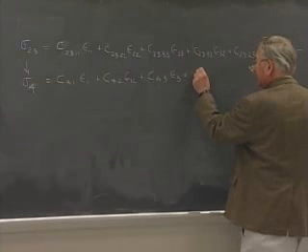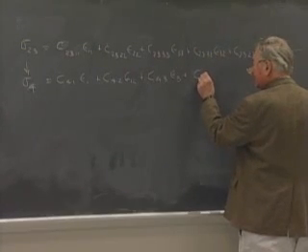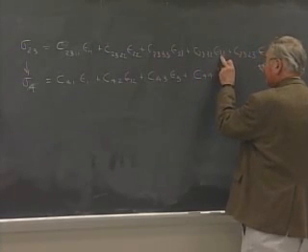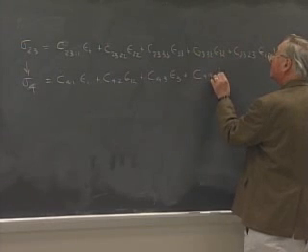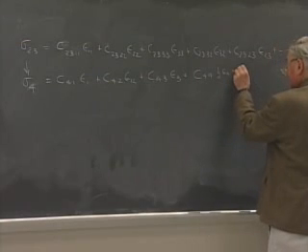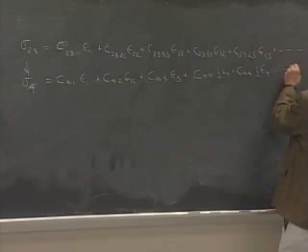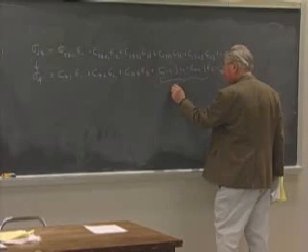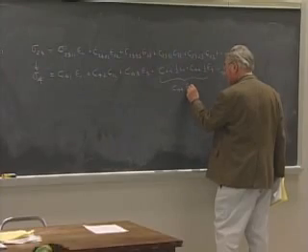And now this matrix element would be C44, and in place of the tensor element of strain epsilon 32, we would write 1/2 of epsilon 4, and the next term is again a C44 times a 1/2 epsilon 4, and the terms in epsilon 5 and epsilon 6 would behave the same way. So you can see that the factor 2 is absorbed, and this becomes simply C44 times epsilon 4.